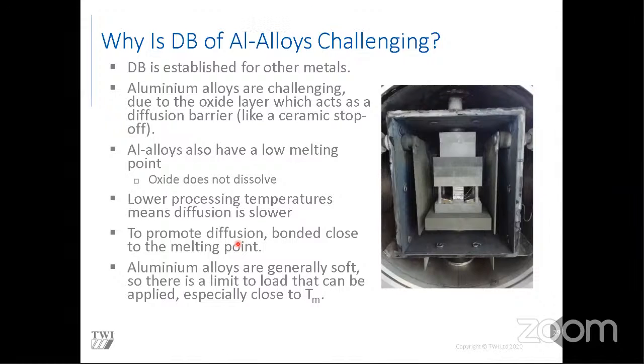What about hardness tests in the mechanical? Yes, we can do hardness testing, you're correct. But because we're quite often doing a mechanical test, a tensile test, there's often not a need to do a hardness test unless we're doing a transient liquid phase bond. Then you'd want to do a series of micro hardness indents through the joint itself, through the bond line, to see if you created any particularly hard or brittle phases.